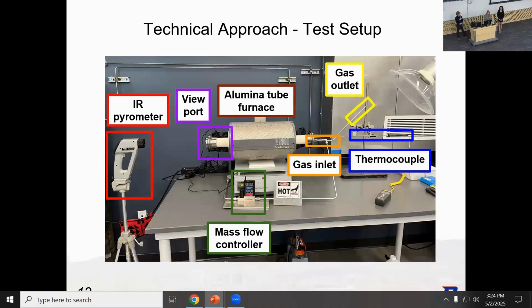So here we can see our actual test setup compared to our cartoon, and we can see we were pretty spot on in how we expected it to be. The only difference we had was the addition of the mass flow controller we can see at the bottom to help regulate the amount of argon gas flowing into our system to prevent that oxidation.